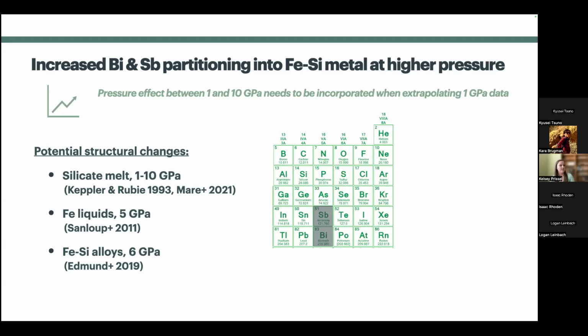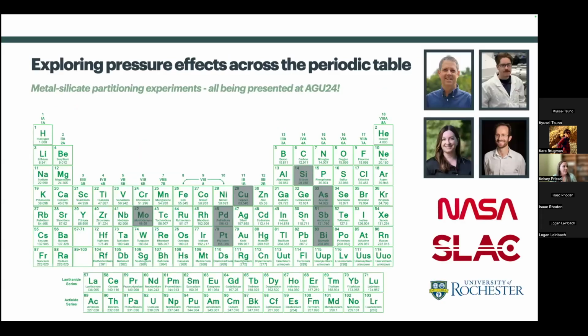Previous studies have hypothesized that there are structural changes both in the silicate melt as well as in the iron melt. And there are even potential structural changes for iron and silicon bearing melts specifically, which might be why we're seeing this effect in our iron and silicon melt series. I want to end by thinking about this problem moving forward, trying to identify why elements behave differently at higher pressures. We studied these 8 elements highlighted here, but we only found a pressure effect for 2 of those 8 elements. I also have my collaborators on this project here: Kevin Ryder, Jake Satera, Justin Simon, and Jocelyn Richardson.